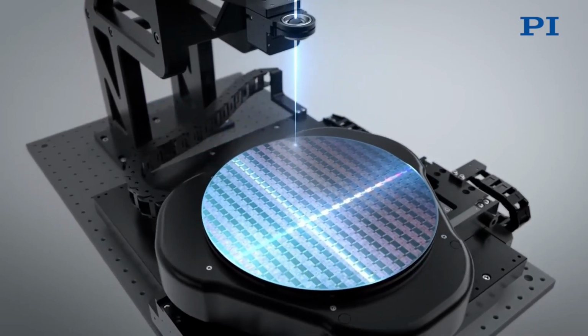In the video, you see one of these chips, a niobium on silicon coplanar waveguide with half the resonators covered. Besides the new material deposited on top, this resonator design is exactly what I showed you before. And you can use this resonator design to determine what the dielectric constant of this newly deposited material is, or at least what it is as this thin film on top.